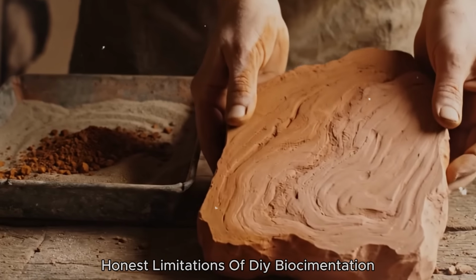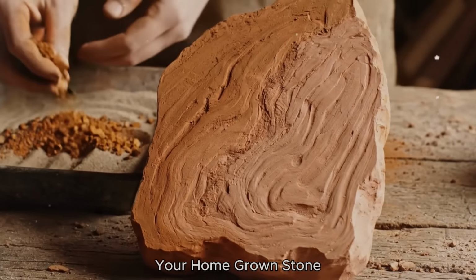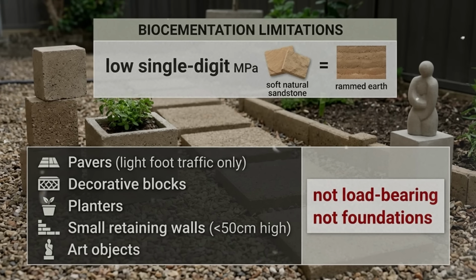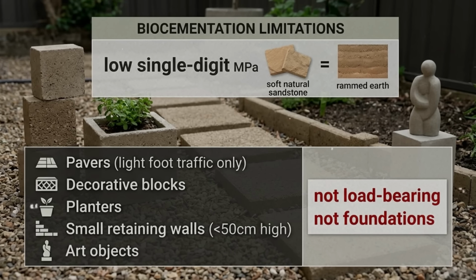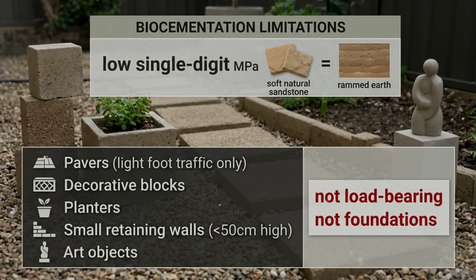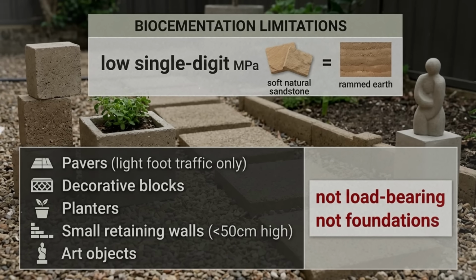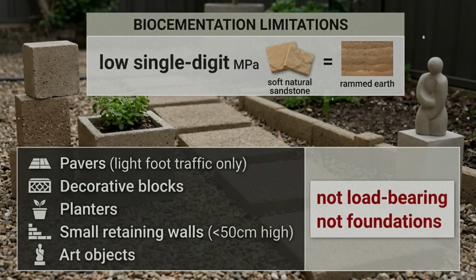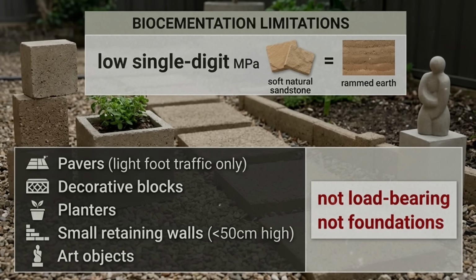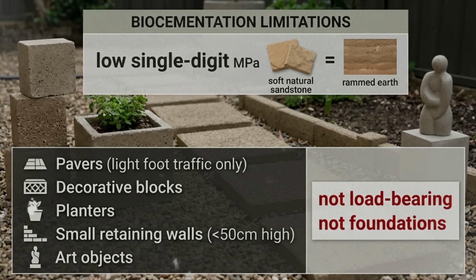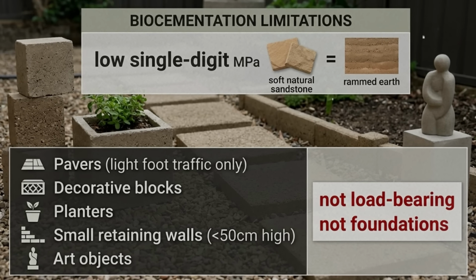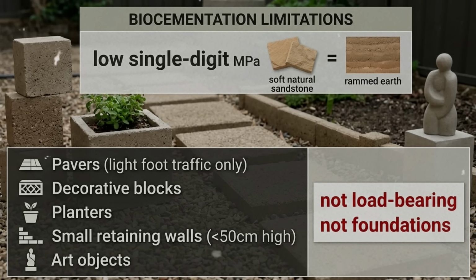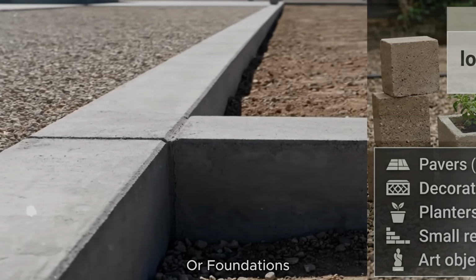Honest limitations of DIY biocementation. Your homegrown stone will not be structural grade material. Expect compressive strength in the low single-digit megapascal range, roughly comparable to soft natural sandstone or rammed earth. This means it is suitable for garden pavers, decorative blocks, planters, small retaining walls, and artistic objects. It is not suitable for load-bearing walls or foundations.